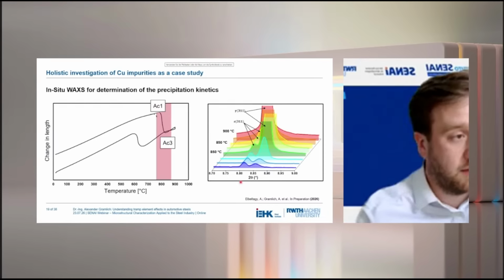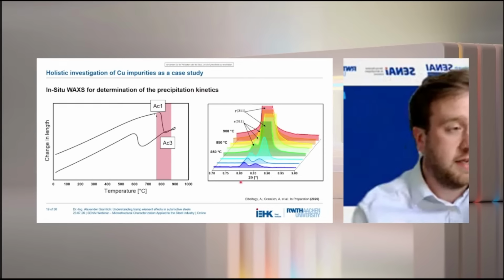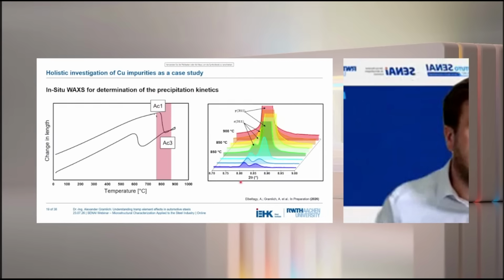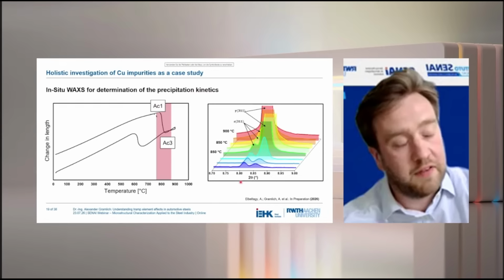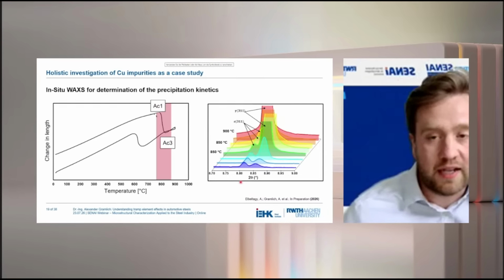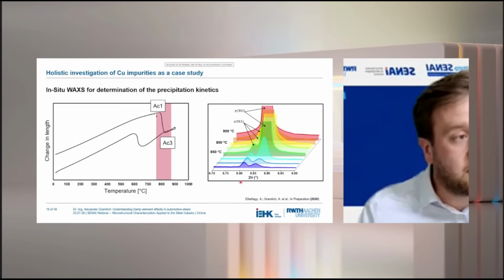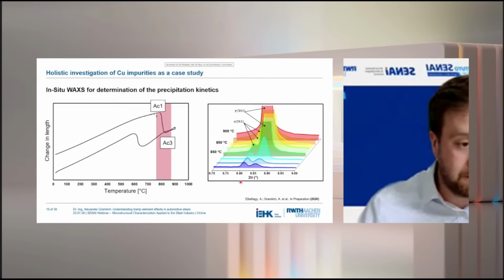And what we are seeing here is the main austenite peak. And during the quenching already, you can see that a small secondary peak is developing on the left of this main peak. Basically, while austenite is transforming into ferrite, you see a very, very small peak in the vicinity of the austenite peak. And this peak is basically FCC copper. And with these results, we could prove that in ferritic steels, you also have, in some cases, direct precipitation of this FCC copper. So we are challenging here what is currently more or less the state of the art. But of course, this is very important as all of our modeling approaches basically need this data to come up with predictions of how the copper precipitates are growing in your industrial steels.